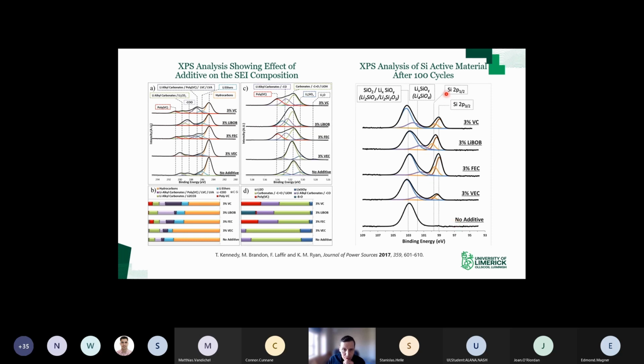Okay, for all the other ones with the additives, fair enough, we did find those silicates as well, but we were able to detect elemental silicon. So below the surface, or at least within 10 nanometers, we were able to detect elemental silicon. So it gave us a good indication why, as I said, the no additive doesn't form that stable ligament structure, whereas the additives do.